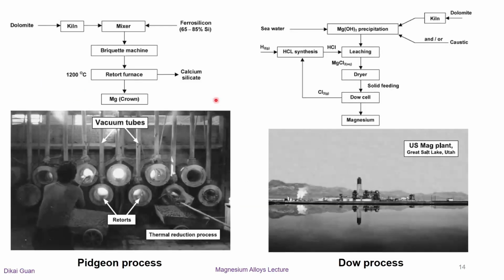The left part shows the flowchart and image of the Pidgeon process. This process uses horizontal steel tubes called retorts in furnaces and under vacuum. In the retorts, mixtures of finely ground calcined dolomite and ferrosilicon form into briquettes and react to form magnesium vapors, which are condensed and later remelted into ingots.